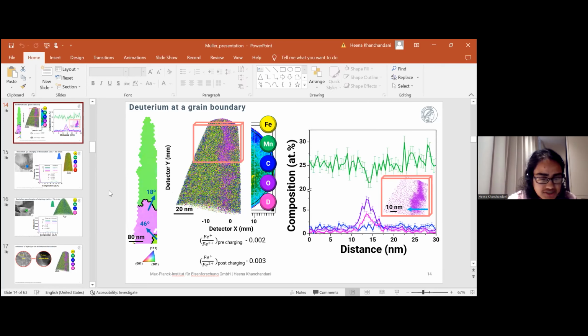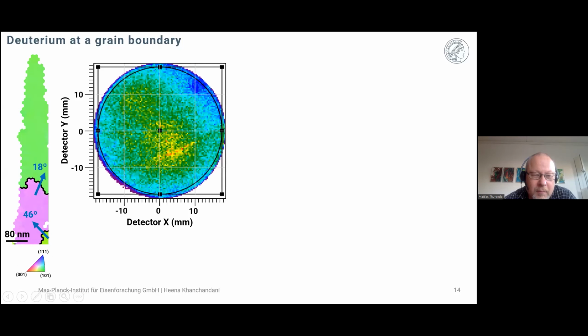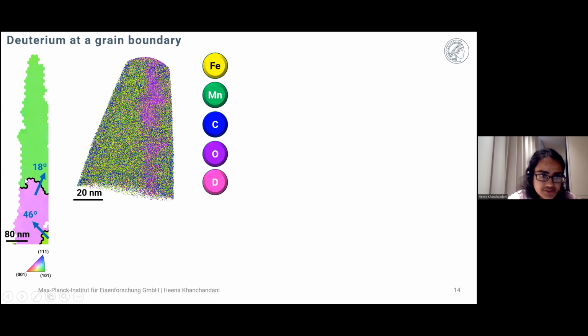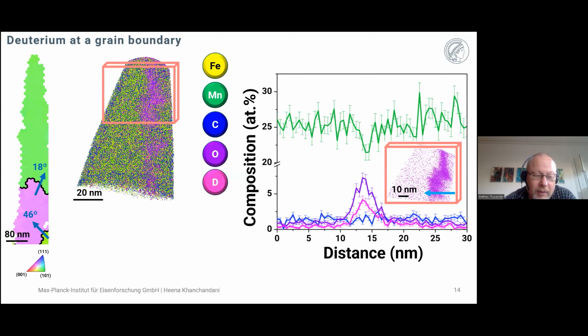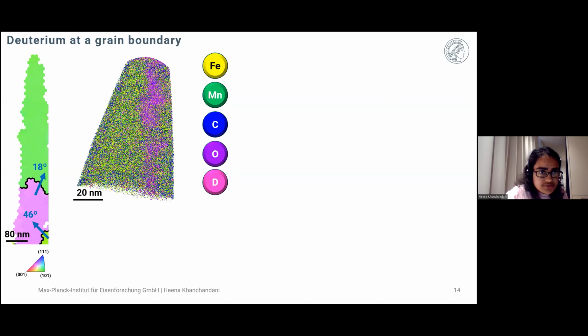So even in the TKD, I'm not sure if you can still see my... Yeah, I see. Yeah, so this one, even in the TKD, it shows this faceted structure. So this grain boundary is not really straight. And yeah, this has faceted and wide structure. But the reason that it looks so wide is that it is wide, or is it so faceted? It is wide. Yeah. So it is not this wide because of the trajectory aberrations. It is wide. This is what we have observed for some grain boundaries in ECCI also. Maybe this one, if I can show in one of these.